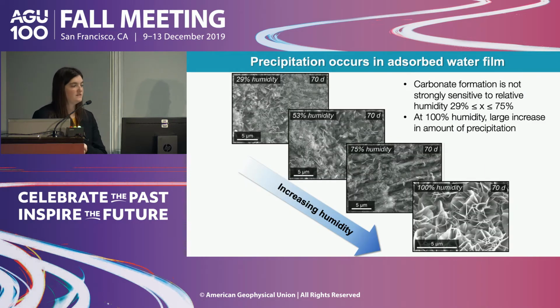And so what we observed in these experiments was, first of all, that both dissolution and precipitation could be facilitated just in these adsorbed water films under all humidity conditions. So we didn't need liquid water contact to have a wetted surface area. We did, however, find that the extent of reaction, again, was extremely sensitive to the relative humidity.